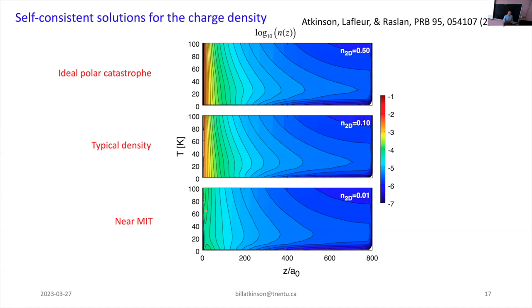And it's a kind of funky universal structure. Initially, when you start at zero Kelvin and you start raising the temperature, what you see is that the electron density spreads away from the interface. And that makes sense. You're thermally exciting your electrons. They're going to spread away from the interface. But then as you go to higher temperature still, the electrons start moving back towards the interface. And that is kind of odd. I'll tell you right now, qualitatively, it's because your dielectric function is dropping as you raise the temperature. That means that the electric fields are no longer screened as well, so the confining potential gets stronger.